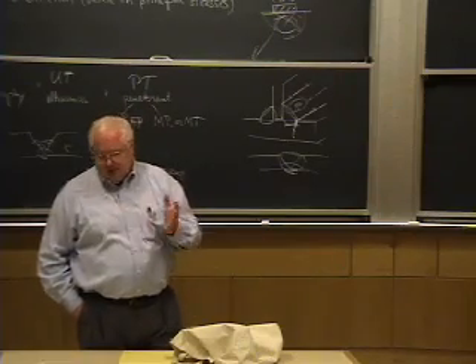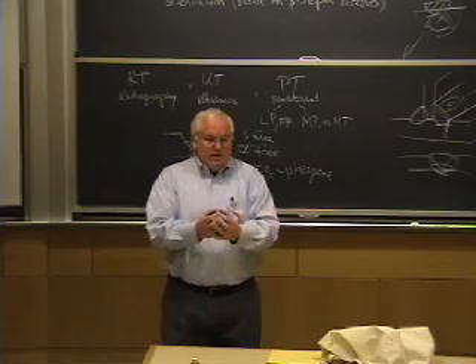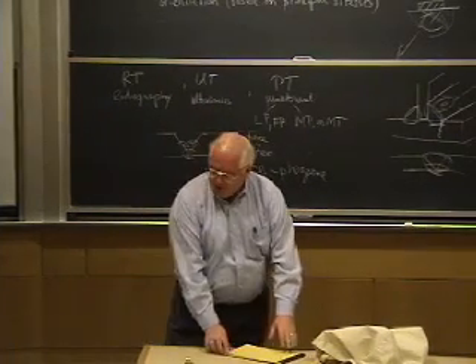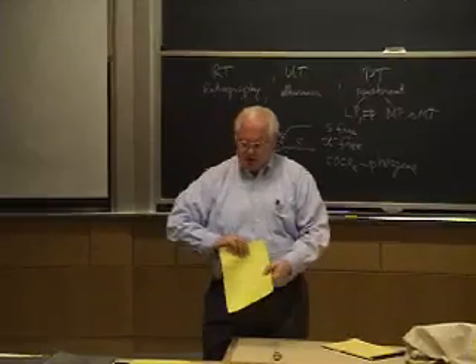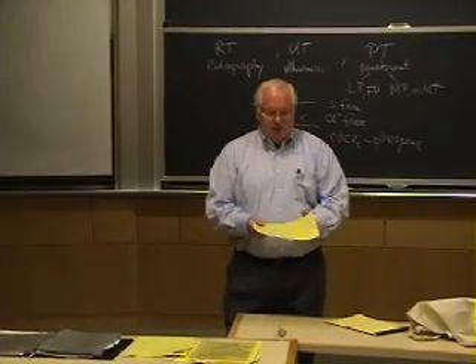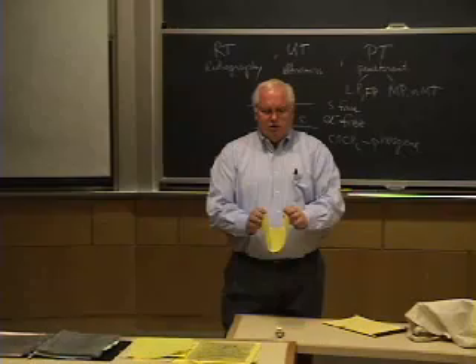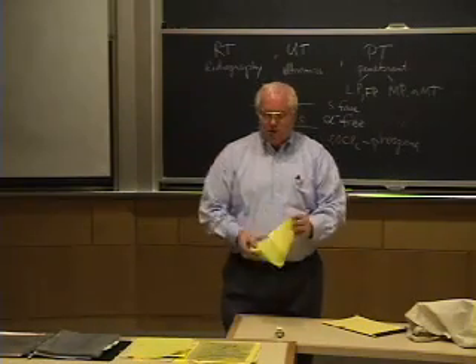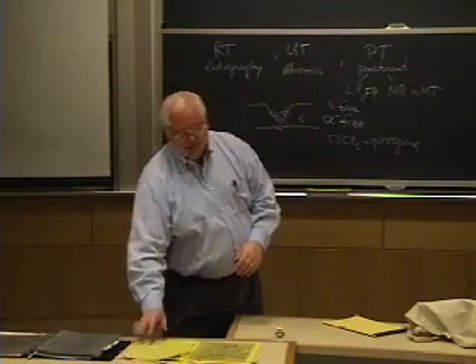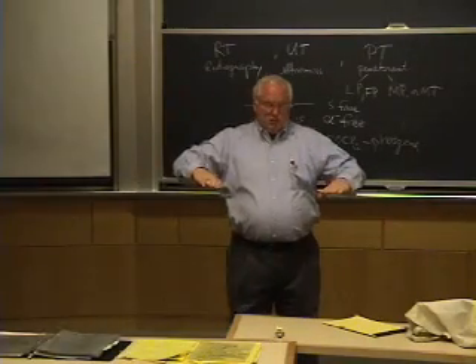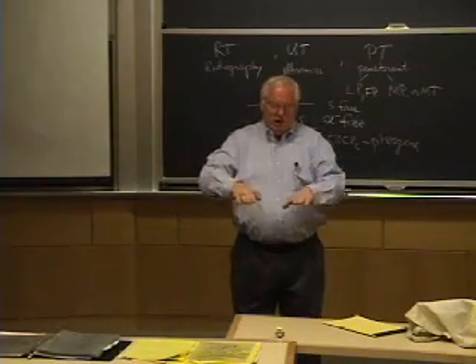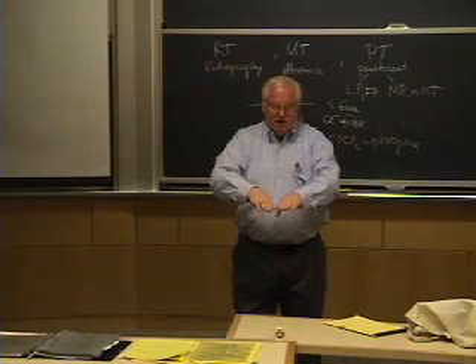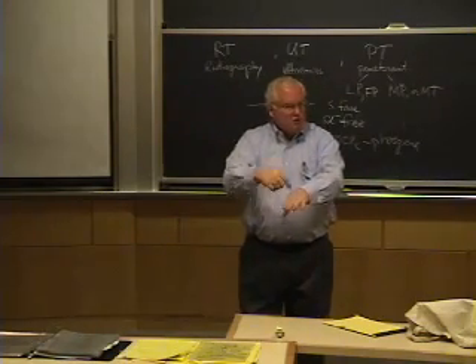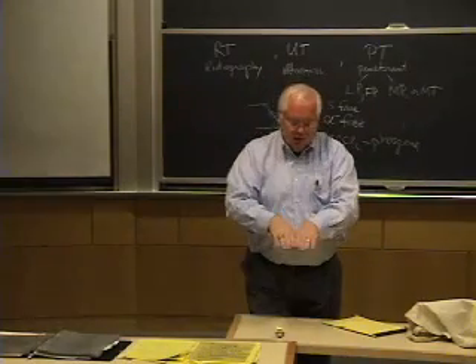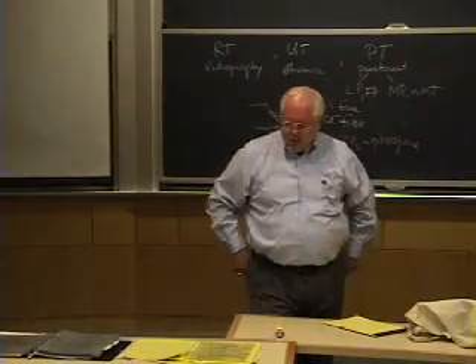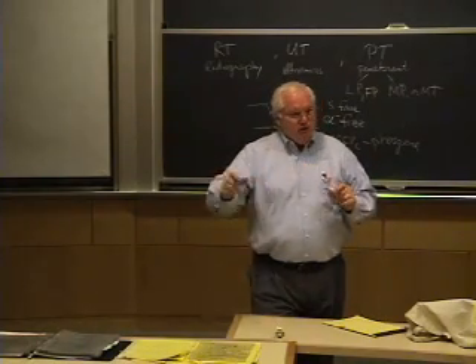When's it used? Well, it's used when you're welding, making steel tubing. You take stainless steel, and I think if you remember, I talked about U and O pipe. You basically take a sheet of material and you roll it up into a U, and then you turn it into an O, and you weld the seam. Well, if you do that, let's say on stainless steel pipe, you use a gas tungsten arc, or an electrical resistance pipe where you basically use a high frequency induction heater, and you bring the sheets together like this and kind of forge them while they're being heated by an arc, an inductive arc, between there, and you forge weld them together.